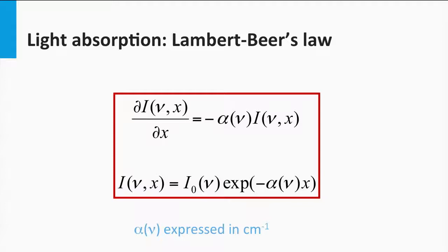For a solar cell, we would like the absorption to be 100%. In this condition, the absorber would be called optically thick. This means the transmission is 0%. From Lambert's law, it can easily be seen that this can be accomplished by either large values for the thickness d, so very thick films, or large values for the absorption coefficient.